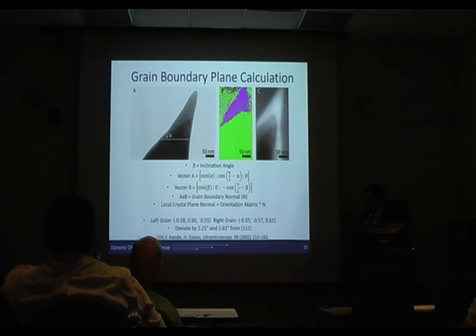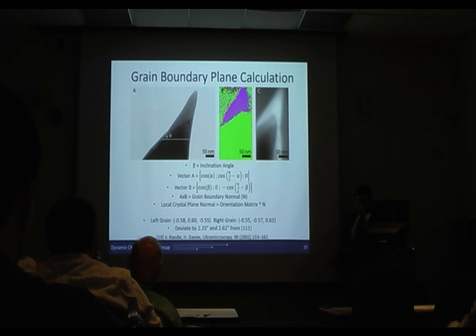However, we do have our ACOM system. So what we can do is we tilted the grain boundary so that it's parallel to the beam. And that angle is then beta. In this case, it's 0 because it's parallel, but if you know your angle, or if you know your thickness and you can measure the width, you can calculate that. Then you also measure this alpha between the grain boundary and the x-axis. And then you vectorize those in vector A and B, and the cross product of those is your grain boundary normal. And if you multiply the orientation of either grain by that normal, you end up with the local crystallographic faces of those grain boundary planes.